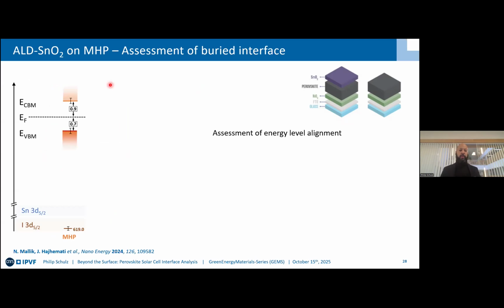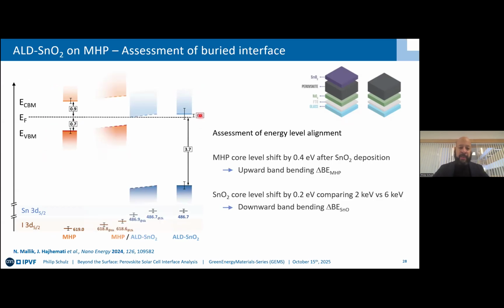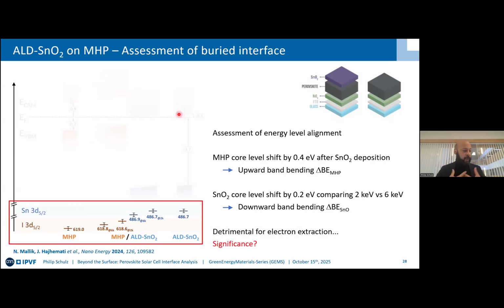And what you then do in order to reconstruct your energy diagram is you assume the perovskite to be intrinsic. We've actually also measured this. Then you see your N-type tin oxide, and in between you get some data points that would hint at upward band bending in the perovskite towards the interface, and downward band bending from the tin oxide. The question is whether this is actually a valid approach, and eventually we refrained a little bit from this, as yes, this would be detrimental for electron extraction, but given that we have this significant chemical restructuring at the interface, we would refrain from making a solid statement about this.